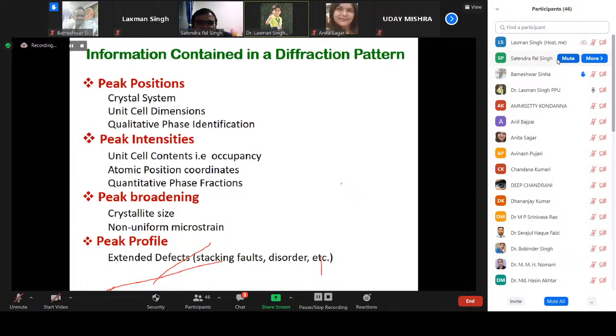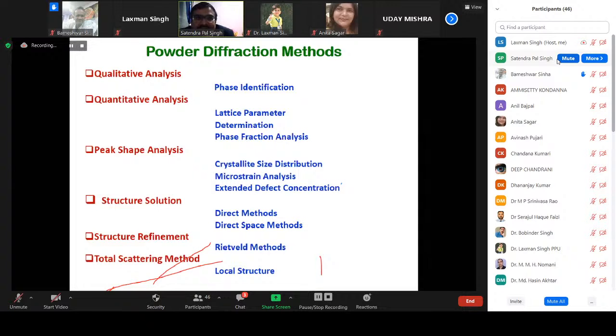Okay, so by knowing the peak positions, we can determine the crystal system, the unit cell dimensions, and do qualitative phase identification. By seeing the peak intensity, we will be able to confirm the unit cell content and atomic positions. The peak broadening will give the crystallite size and non-uniform microstrain, and the peak profile will give the extended defects. So these parameters in the XRD patterns are essential and very helpful in identifying any crystal system. And what analysis can we do from that? From the powder diffraction method, we can do qualitative analysis.